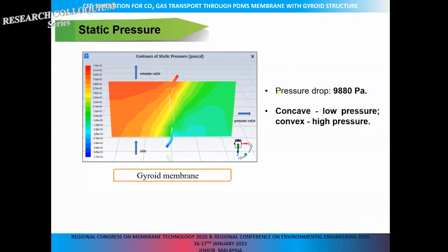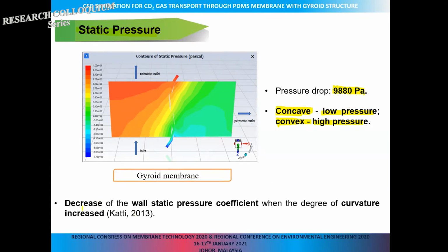So now I will present the results and discussion. For our hydrodynamic profile, we will evaluate based on two aspects: one is the static pressure and the other is the velocity magnitude. For the static pressure, you can see from the profile here that when the membrane is at the concave side, it has a lower pressure, and when it reaches the convex side, it has a higher pressure. Then we can see that the pressure drop is about 10 kPa. This is mainly because of the decrease of the wall static pressure coefficient when there is an increase in the degree of curvature. So it means that the hydrodynamic profile or the pressure distribution within the membrane can be affected by the curvature of the membrane.